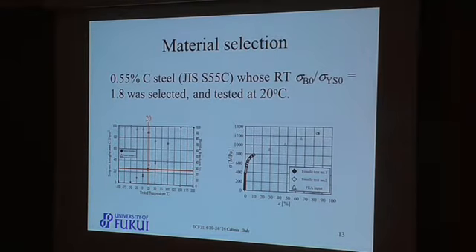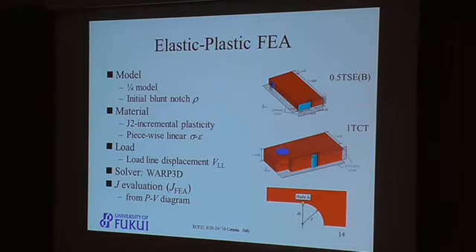Given that the room temperature tensile to yield stress ratio of the European RPVs and Japanese RPVs is 1.3, 0.55% carbon steel JIS S55C, whose room temperature stress ratio is known to show a higher value of 1.8, was selected for examination and tested at 20 centigrade. The Charpy impact test results and tensile test results are shown in these figures. 0.5TSE(B) and 1TCT specimens were examined. The details of the EPFEA are summarized on this page.